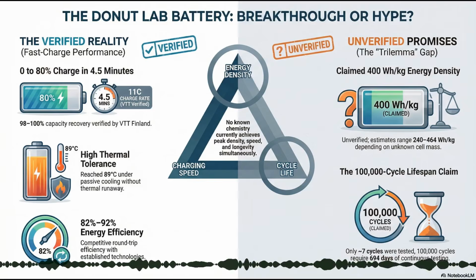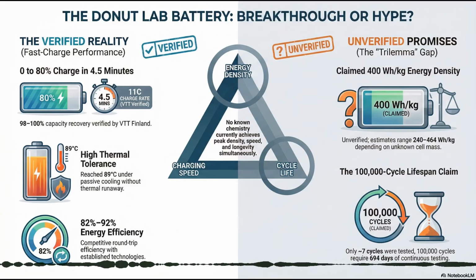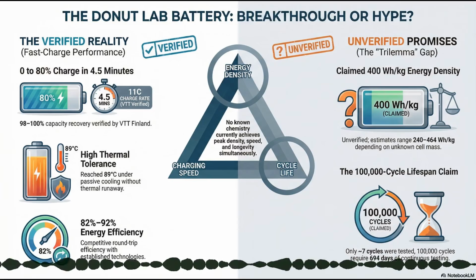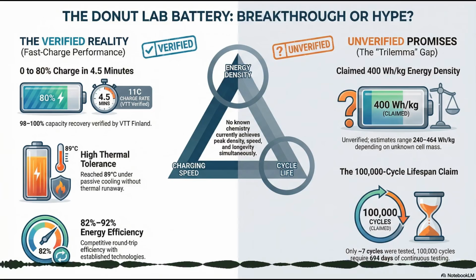Exactly. Imagine a rigid concrete wall. Now imagine something inside the wall trying to expand by 10% every few hours. The wall cracks. If you have a rigid ceramic solid electrolyte and a breathing anode, eventually something is going to crack. Or the interface delaminates. Right, it peels apart. At 11C charging, that mechanical stress is violent. You are stripping ions so fast you create voids, empty microscopic spaces at the interface, leading to loss of electrical contact. Once you lose contact, the cell resistance spikes and the cell dies.